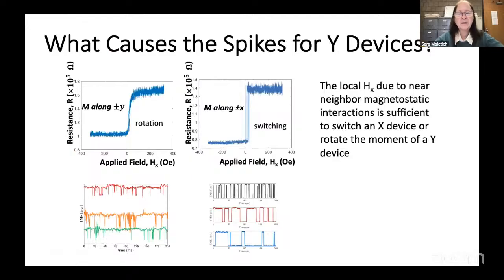However, these magnetostatic calculations do not explain why you have spikes. The spikes, we believe, are associated with this easy axis, hard axis behavior. With a sharp magnetization or resistance curve, you get actual switching between 0 and 180 degrees back and forth. With the hard axis curve, you're not switching. The magnitude of the fields that you get from these near neighbor interactions is in this range where you're getting rotation, but you're not saturating at either of these states. And in fact, saturation in this case would be lying along the X direction. That's a very high energy state.